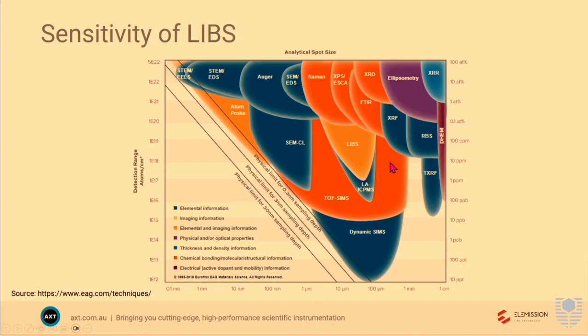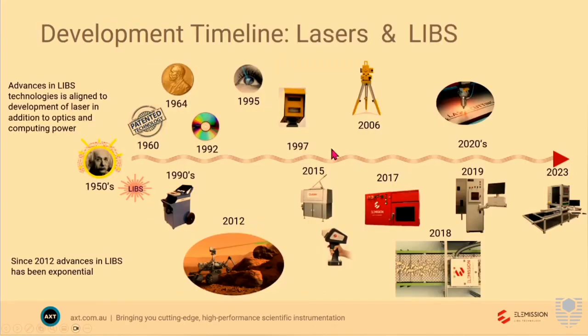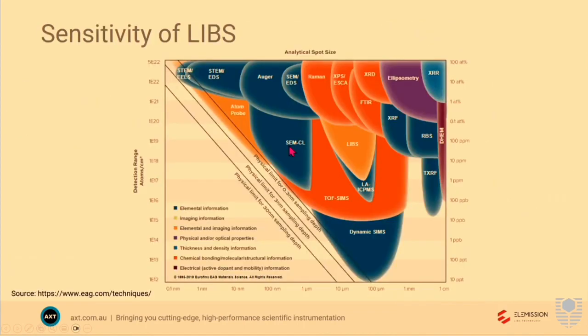So it's saying that the resolution is in the order of 10 microns, so the analytical instruments are sort of 10 to 50 microns. It's got moderate sensitivity, so it's not as sensitive as laser ablation ICP-MS or TOF SIMS or dynamic SIMS, but it's more sensitive than other techniques, so SEM-EDS. There's a lot of other acronyms there which tend to only be used in the high-end university application.